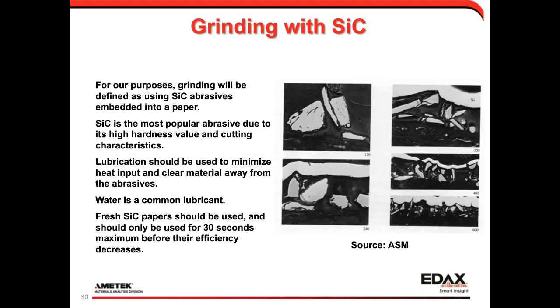And so when I talk about grinding, basically I define this as when I'm using silicon carbide abrasives embedded into a paper. And so I think silicon carbide paper is probably the most popular abrasive for grinding because it's high hardness, good cutting, and relatively inexpensive. You should use some sort of a lubrication to minimize the heat input and keep the abrasive clear. I commonly use water for materials that will tolerate it.